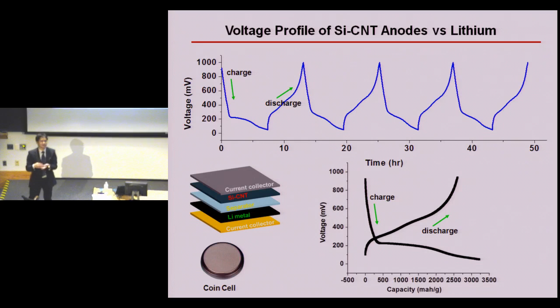So after we have this excellent core-shell structure, I started to make batteries out of this structure using a coin cell device. So basically, I have silicon carbon nanotube function as a negative electrode. I use lithium metal as a reference electrode. Basically, for this two-terminal device, we apply current and we measure the voltage change. And because silicon is an active electrode, as we charge the battery, the voltage will decrease. And then we switch the direction of the current. So that means we start to discharge the battery, and the voltage will increase.